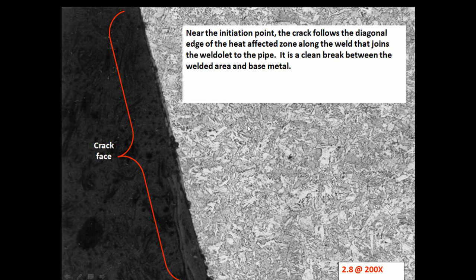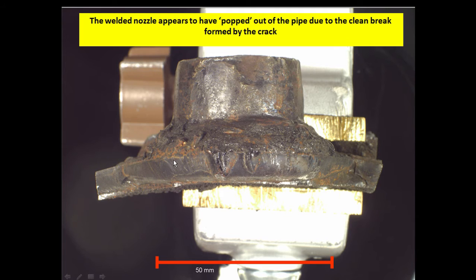This right here is the RT. This is actually metallographic analysis, and this shows the crack edge here. It follows the diagonal edge of the heat affected zone, so it's at the fillet. Now, we didn't cut this out. We went over with a ball peen hammer and just basically tapped it and it popped right out.